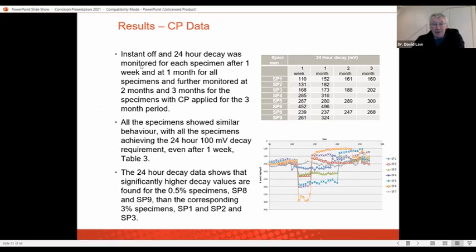Looking at these, and here we can see this in a little more colour, when we did the testing, these are the criteria to determine if it's protected. We found that all the specimens were actually being protected by the cathodic protection when we tested them with their instant off, which is how you check for those. We also saw, unsurprisingly, that the 0.5% specimens were giving bigger decay values, so they were showing better protection than our 3% specimens.